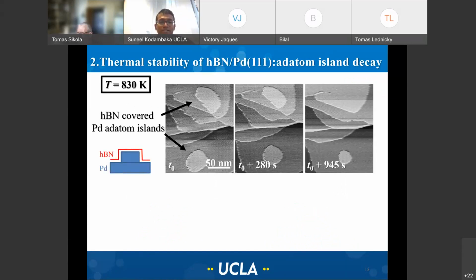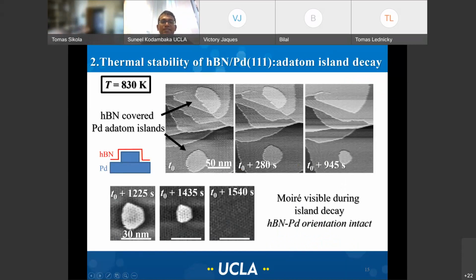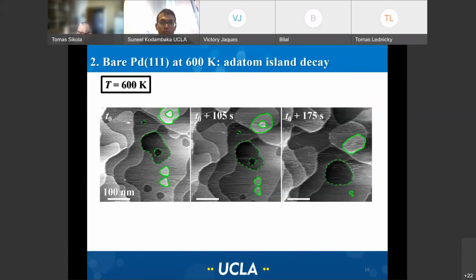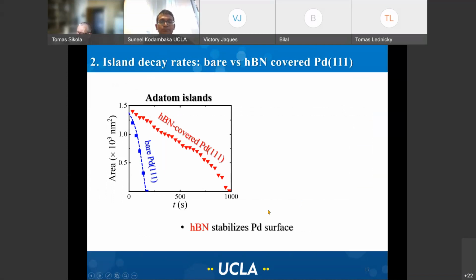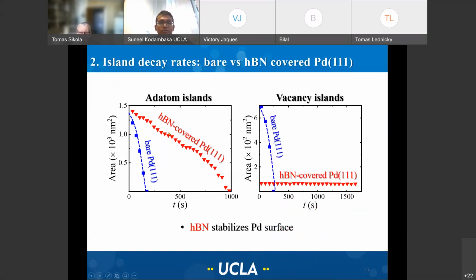Another interesting aspect is that if you have monolayer boron nitride covering the surface, the islands decay at a much slower rate while retaining the same surface orientation. So the layer on top does not get distorted as the palladium islands disappear. Whereas if you have no covering, no monolayer boron nitride, then the islands decay at a much faster rate. Okay, so this is a summary of those observations with both adatom islands and vacancy islands. On bare palladium, they decay significantly faster than if you have an hBN layer covering the surface.